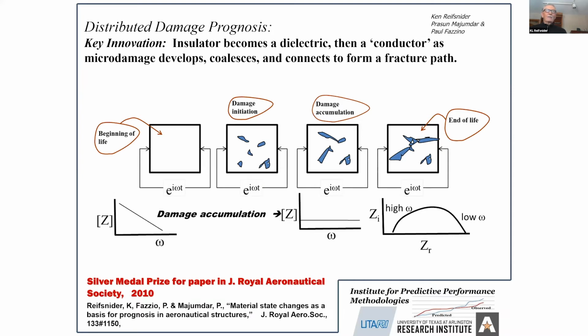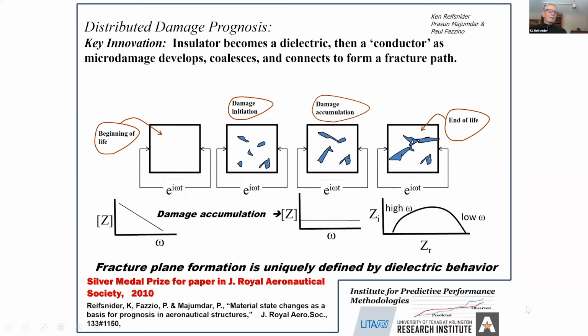And there's a lot of dependence on frequency when there's a lot of polarization as the damage accumulates. But as it begins to accumulate, it begins to couple up. And by the end of life, there can actually be a conduction path between the left-hand side and the right-hand side. So then the frequency dependence is zero, as we saw. It's essentially a copper wire. There's some conductive path from left to right. Remember, he's putting in conductive material to see where that plane is going. So the conclusion of this was that the fracture plane formation is uniquely defined by dielectric behavior, and this took the silver medal in the Aeronautical Society in 2010.